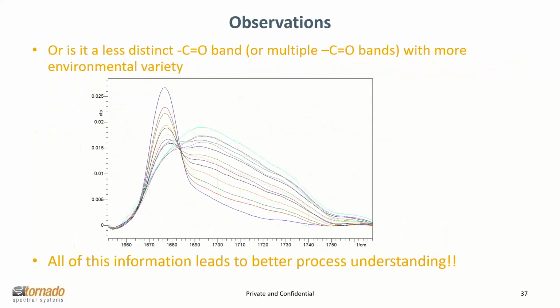Or we can look at this a different way. If we process the data a little bit differently, maybe we still do see a carbonyl band that's much broader and much less intense compared to the original carbonyl band that we see in the starting form 2. So again, relating this to some of the other data like X-ray, you can start to piece together some molecular information about the crystalline form that you're seeing. So all this information leads to a better process understanding.